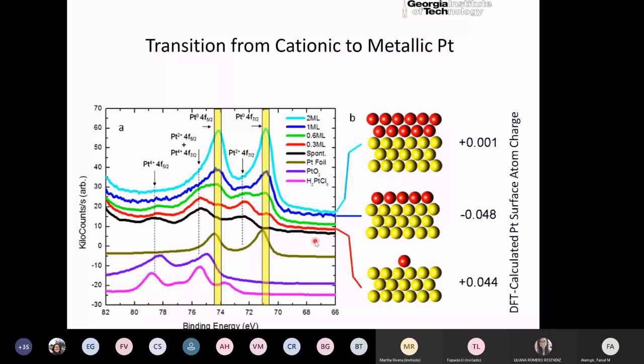The third part of this might be what you're asking, might be about coverage. How do you know that you're fully covering the graphene or partially covering the graphene and so forth. And for that, you could use electrochemistry. So you could look for a key reaction of the material that is underneath the platinum. If that key reaction shows up, that means the platinum is not covering that material completely. And we used that idea when we were looking at gold, graphene, platinum stacks.